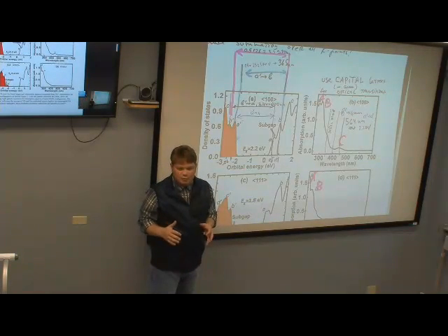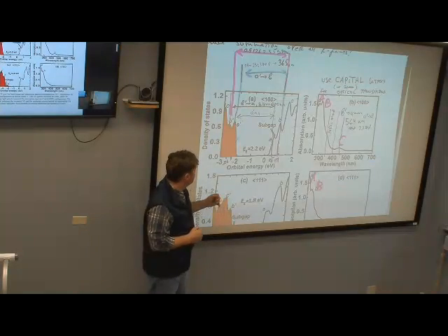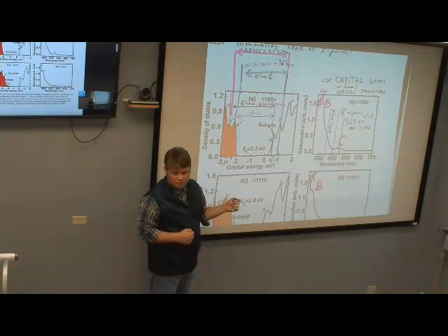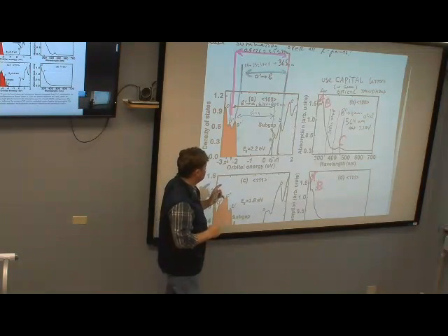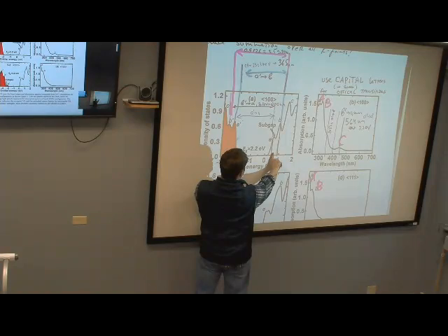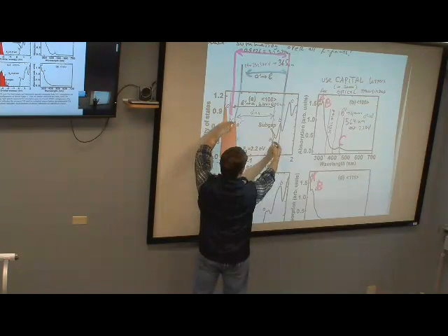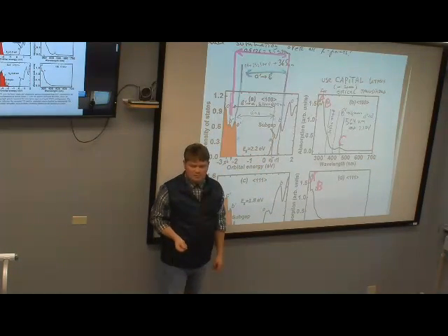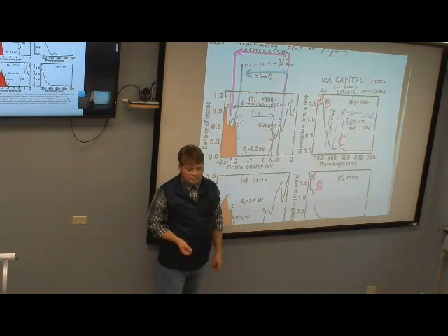Let me expand the question, and then Fatima may answer. Right now we do add width to each line, and this width is so broad that it covers and combines several peaks together. But there is a probability that there are a couple of peaks really at the band gap, and then there are degenerate states a little bit away. The positions of peaks would definitely give not 2.2 but something like 2.9, just looking at this image.